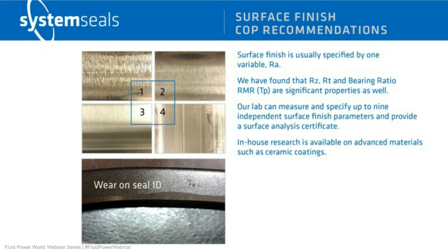So traditionally on engineering drawings for sealing components, we'll often encounter one specified variable, which is the RA, which is effectively a statistical average of the surface profile. But what we found in various surface finish experiments in our lab is that a number of other parameters matter. They're statistically significant. So for example, the RZ, the RT, and the bearing ratio have also shown themselves to be significant and important predictors for seal wear and for sealability in the long term.